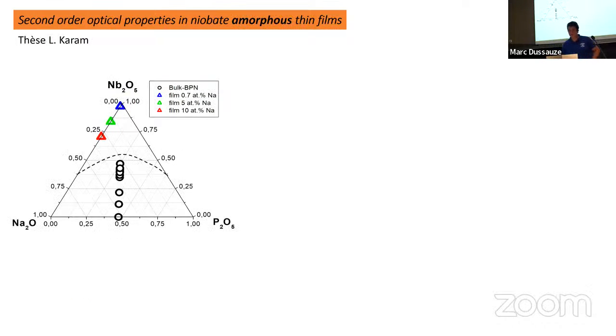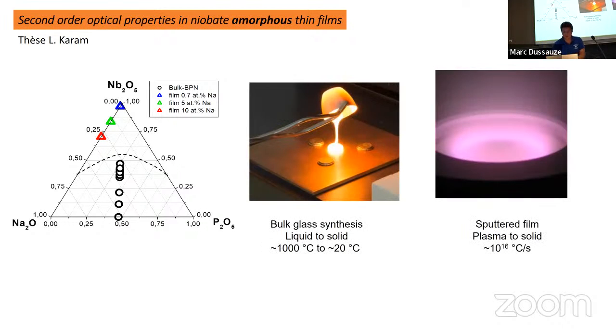I will switch now quite fast to the thesis of Lara Karam, where we have worked on pure niobate films. In order to improve these Chi3 values, we have removed all the glass formers. So how can we make a glass without glass formers? That's a good question. For this, you need to quench much more rapidly. And if you want to quench much more rapidly, you need to go towards sputtering depositions that go through a plasma. Because going through the plasma, you increase the quenching rate by many orders of magnitude, and you can get, I will not say glassy, but at least amorphous materials for almost lots of compounds.